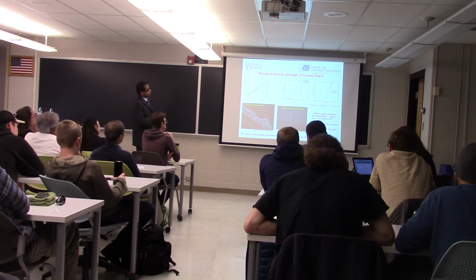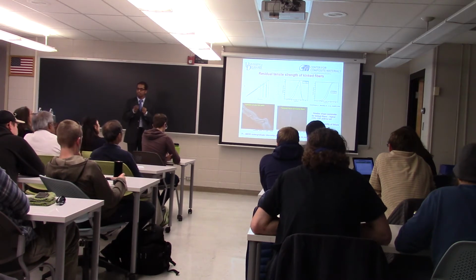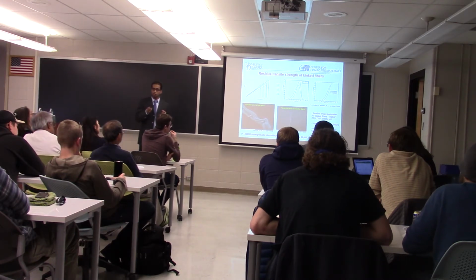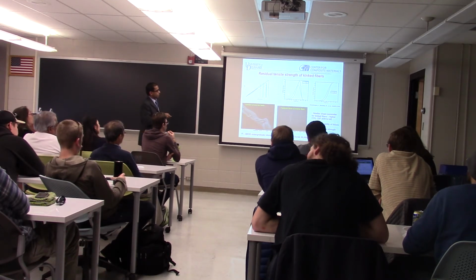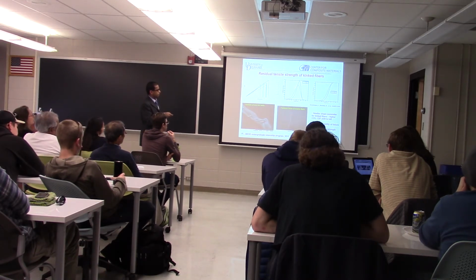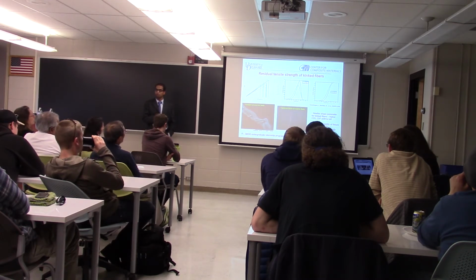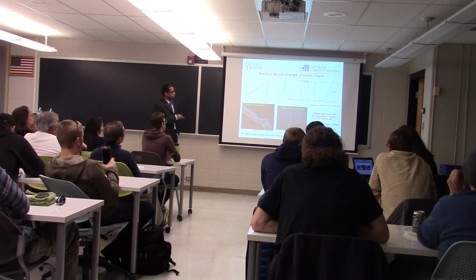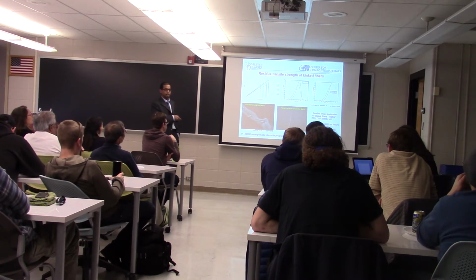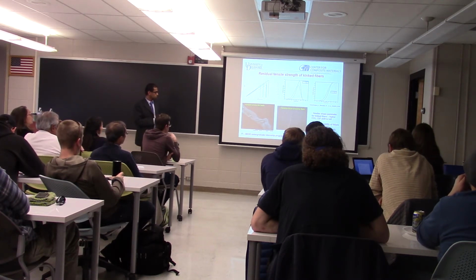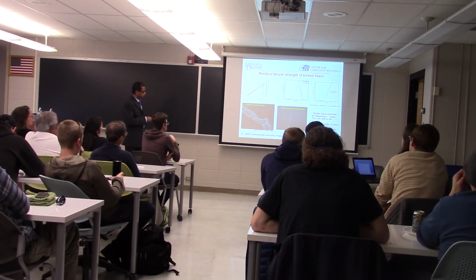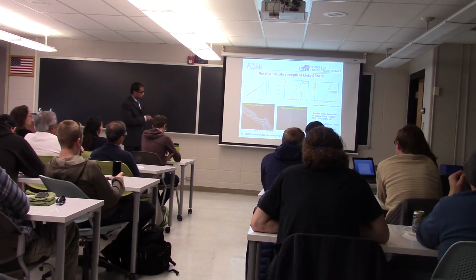So next, we tested these kinked fibers in axial tension to characterize the residual strength of these fibers. A statistical analysis shows a decrease in the average tensile strength compared to baseline fibers. And also the cumulative distribution function shifts to the left, indicating a higher probability of failure. And we see significant fibrillation of these fibers around the kink bands.